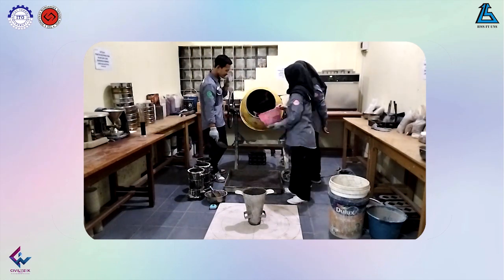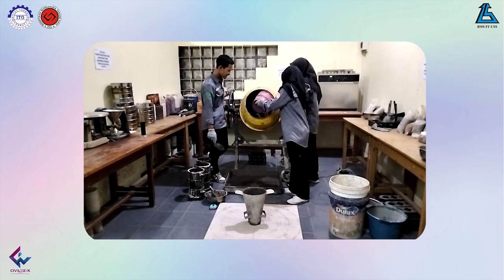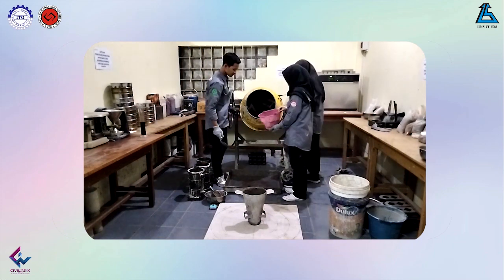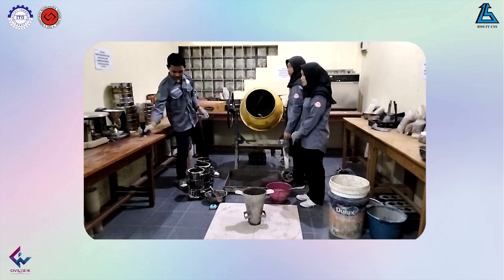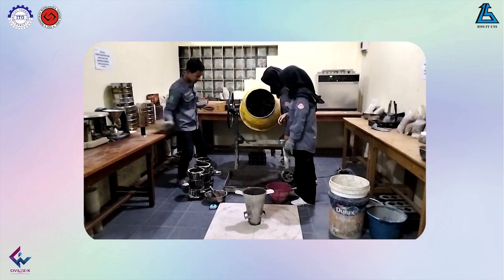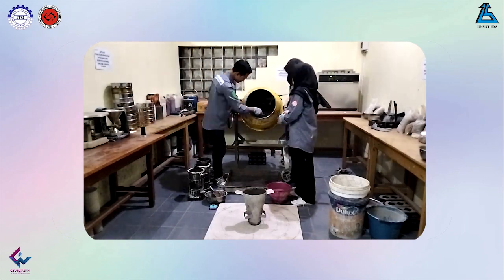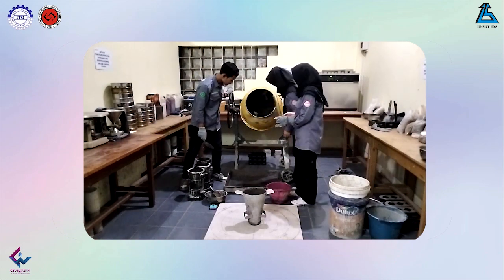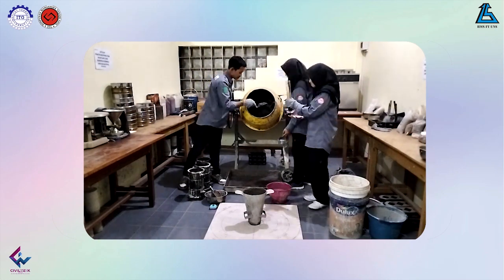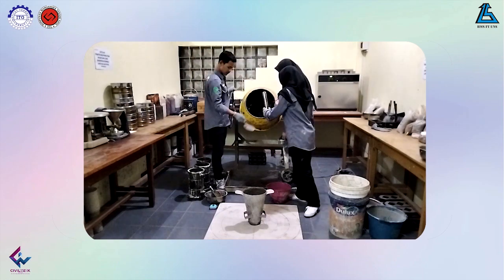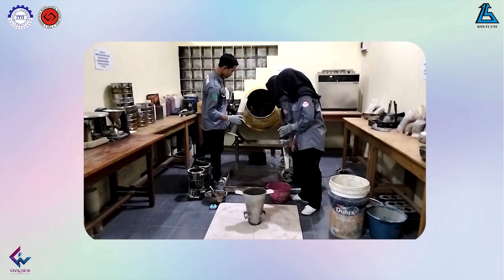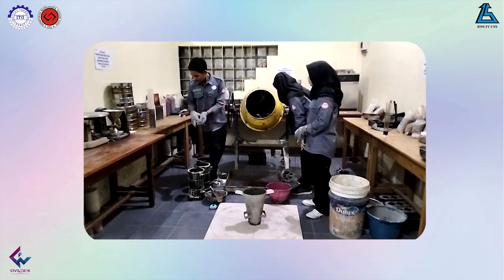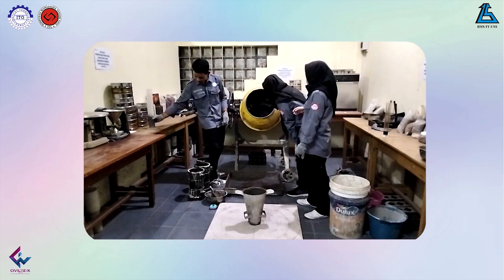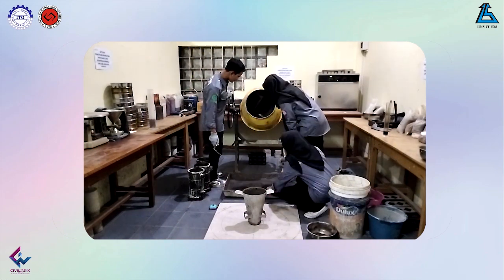0.6 kg of asbestos waste as a partial substitute for fine aggregate, and 0.9 kg of stone ash. Next, add 8.55 kg of cement. The cement we use is Portland composite cement or PCC. Allow 30 to 60 seconds until all ingredients are well mixed.